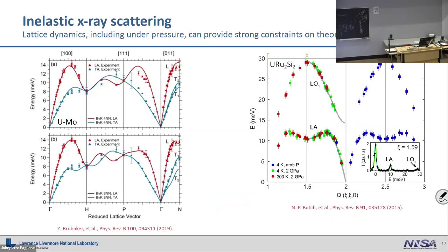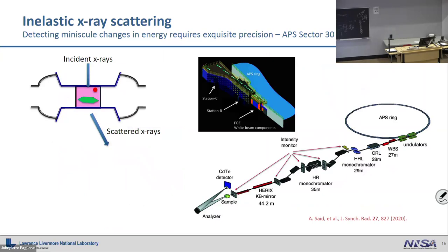So there's a ton of work that goes into how the HERIX works. I guess I can mention briefly, you come in with a monochromatic X-ray. I think HERIX generally runs right around 20 kilovolts. This is one of the most fancy monochromators at the ring. It really has a plus or minus one electron volt or less on the monochromator. And it has to, because it's trying to measure millivolt excitations. So it's coming in with a 20.123 kilovolt X-ray, and it's measuring a 20.123001 X-ray coming out the backside. So it's a 10 to the minus 6 kind of thing that it's measuring, or 10 to the minus 7 in terms of how it measures.